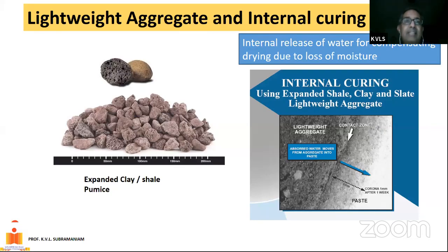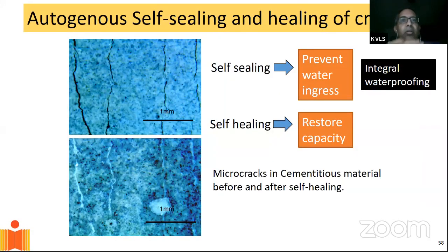But what if concrete does crack? Then now we are looking at autogenous self-healing and self-sealing of cracks. Self-sealing is basically when I have a crack and the crack gets filled up with some material which prevents water ingress, or which prevents water from getting into the cracks. And integral waterproofing essentially lies in this category where I'm able to seal the cracks. Now, but we are thinking one step forward where we are talking about self-healing.